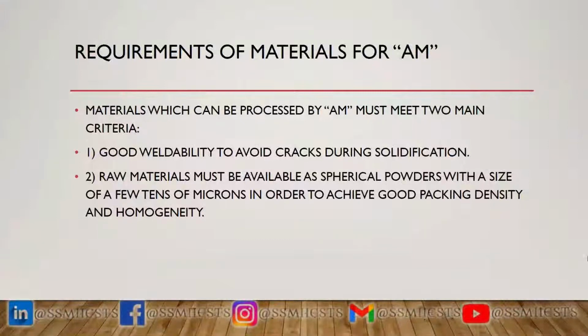Next slide, please. So what are the requirements of materials for AM? Materials which can be processed by AM must meet two main criteria: good weldability to avoid cracks during solidification, and raw materials are very important. These must be available as spherical powders with the size of a few tens of microns in order to achieve good packing density and homogeneity. Next one, please.